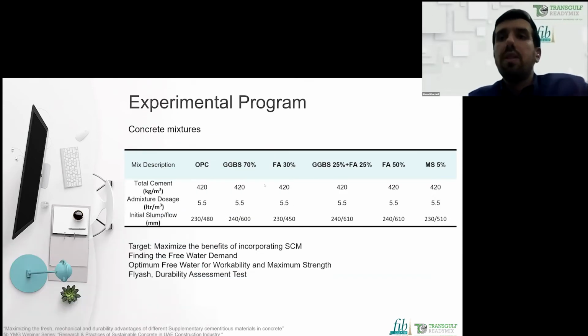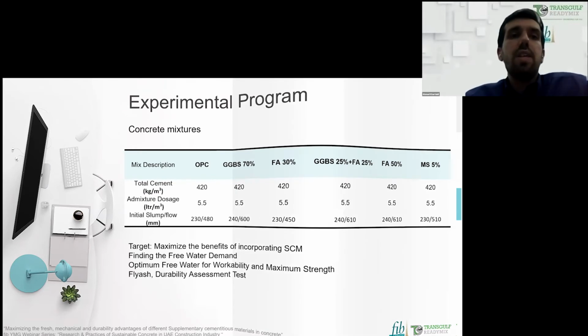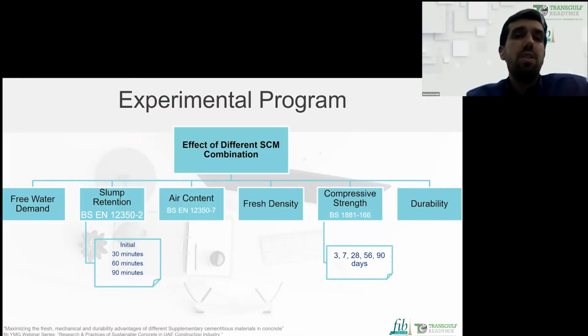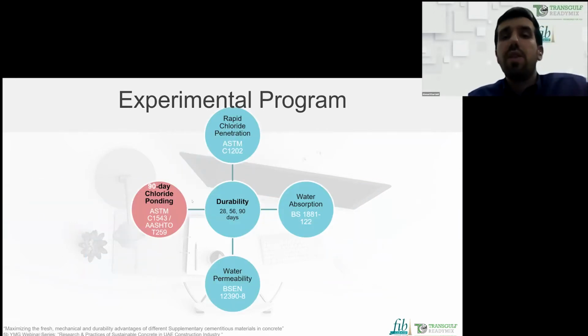So here in this slide, you can see that the admixture dosage is fixed, the cement content is exactly 420, and the initial slump for all the concrete mixes was targeted at 230. As I mentioned, the target is to maximize the benefit from incorporating supplementary cementitious material and finding the free water demand, the minimum free water demand, so what we can call the optimum free water for workability, maximizing the strength and looking into the durability afterwards. In this study, we evaluated free water demand, slump retention based on the free water demand decided at the start of the study, and after fixing the dosage of admixture, air content, fresh density, compressive strength, and durability. Durability is assessed at 3 different ages, similar to the compressive strength: 28, 56, and 90 days.